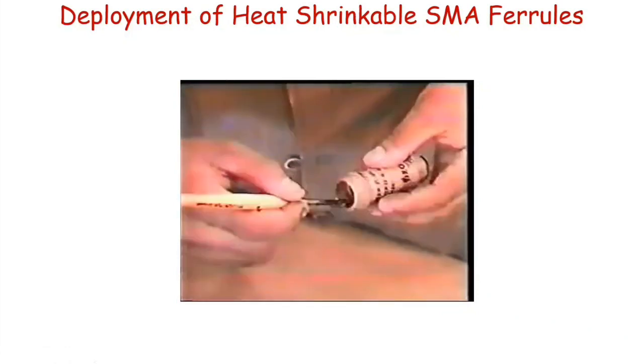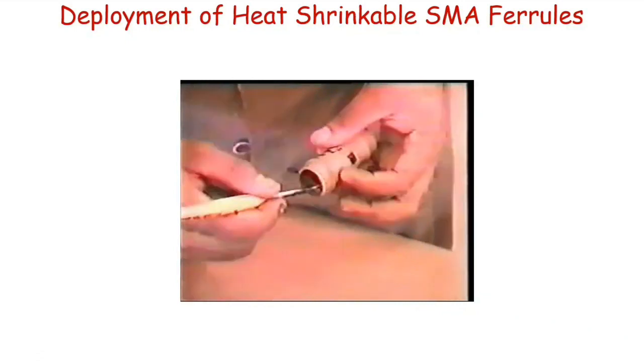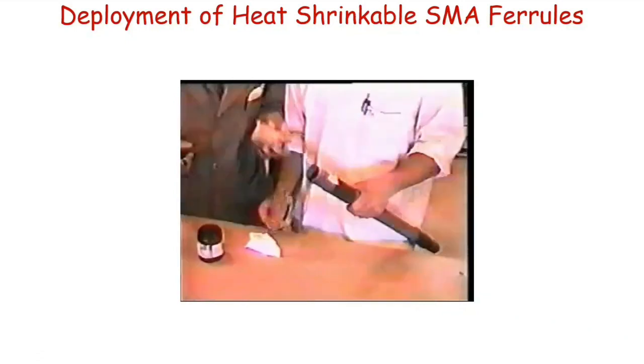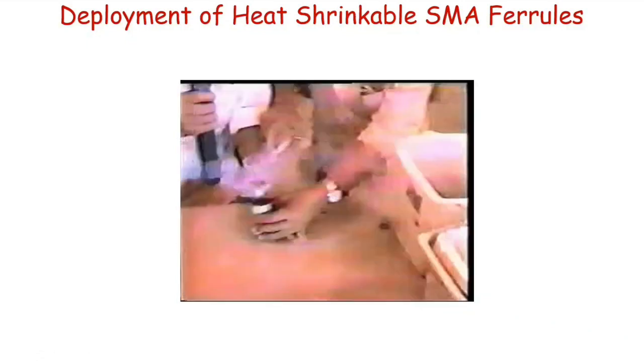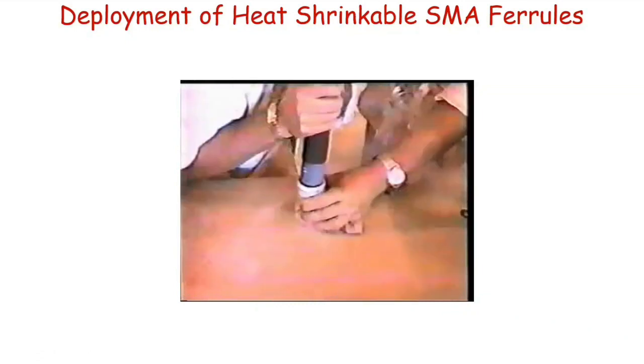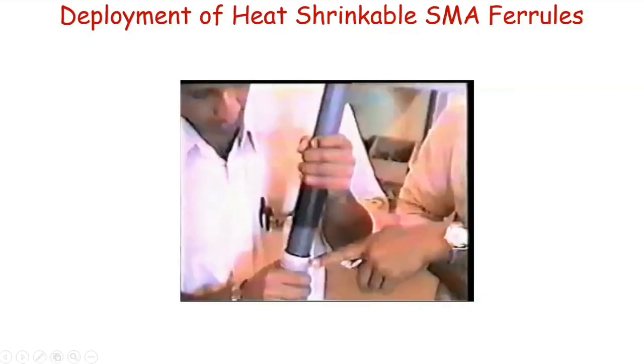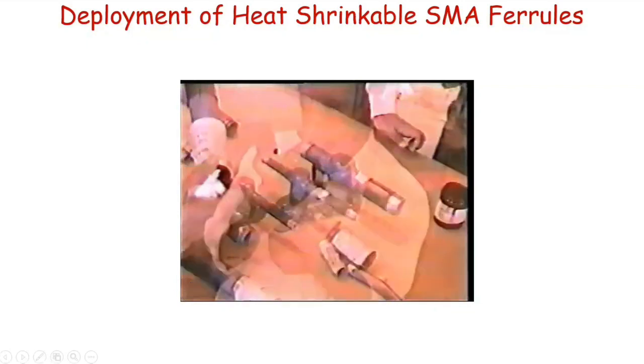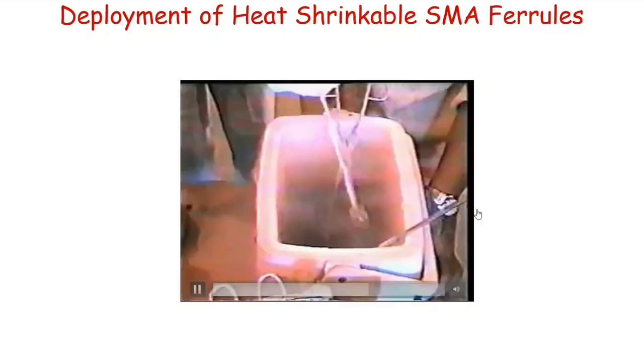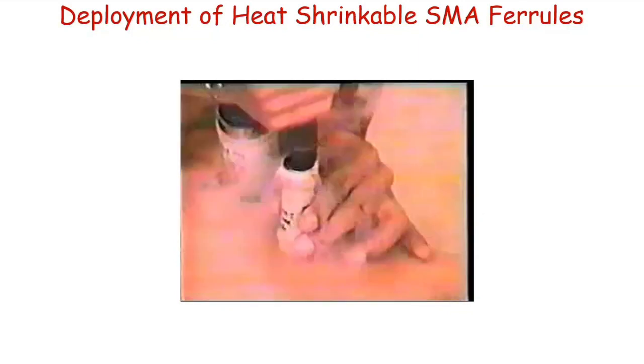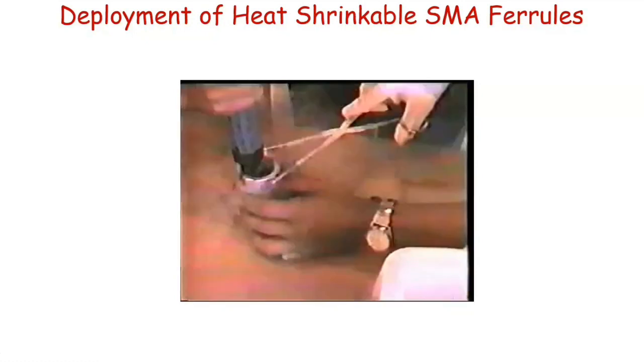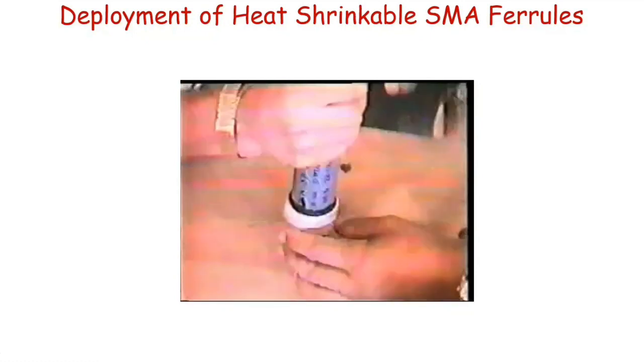So what they do is deform it to something like about 6%, and this is stored in liquid nitrogen till the time of deployment. At that time, here he's stripping off the paint and applying some Bostik sealant to make it gas tight, and in a wink of an eye, you have to be careful to see this, because they use a tweezer or a tong, any low profile tool hardly required. That's it, it's done. The moment it shrinks, it's applying a stress. It's virtually fit and forget, to the extent that if you have to remove it, you have to virtually cut it out. And it's an intermetallic, so you have to put in some effort there.